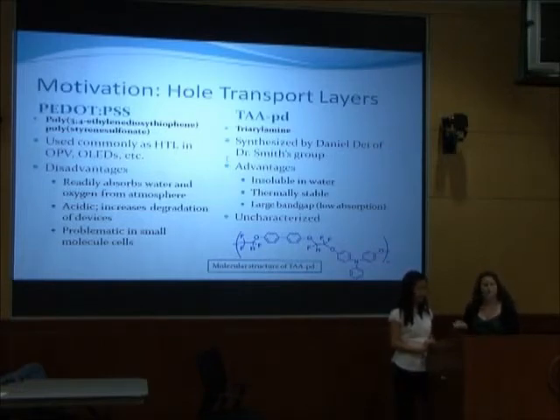The hole transport layers that we used were PEDOT:PSS and TAAPD. PEDOT is commonly used in both organic solar cells and diodes, but it has several disadvantages. It absorbs oxygen and water from the surrounding atmosphere. It's acidic, so it has a tendency to degrade the devices it's in. And it also causes problems in small molecule devices. Because of these disadvantages, we were hoping to replace PEDOT with TAAPD.